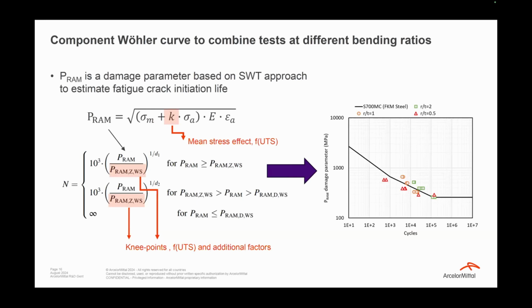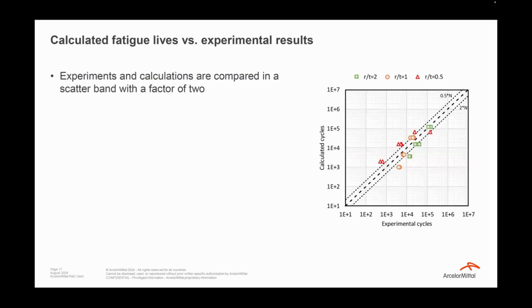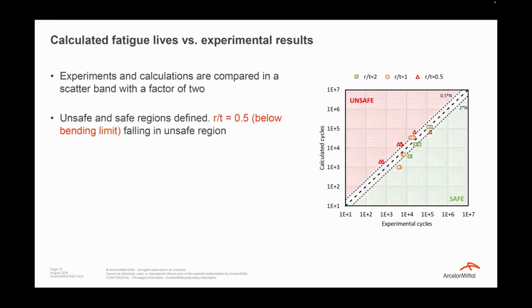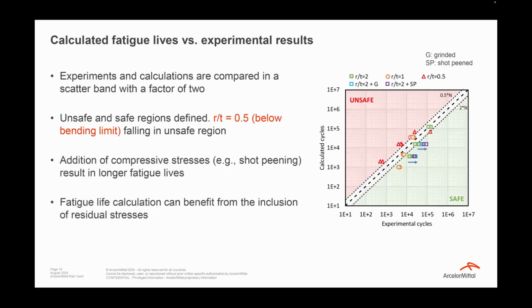And maybe it is better to see these results on a cross-check graph. So now I'm comparing the experiments and calculations on a scatter band with a factor of 2. And then what I can do is I can define some unsafe and safe regions. So this is essentially design space. And it was nice to see that already a good separator is happening for the R over T 0.5, because remember, these were the bend faces with defects, so we expect them to underperform. Once we load, then there should be immediately some crack should start, and then it shouldn't be only the stress concentration factor, but also the initial crack should hinder the fatigue performance.